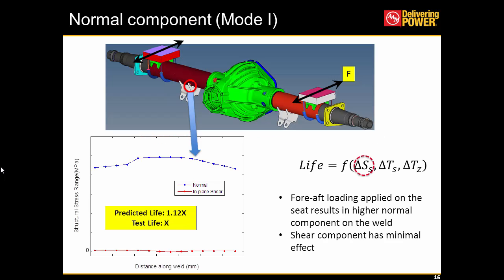So first, I have a situation with a mode 1 dominant scenario. In this case, we are able to predict the location of which weld is going to fail. In this particular case, a rear axle where the shock bracket weld is failing, it's dominated by normal structural stress. The shear effect is minimal, and we are able to predict it pretty well against the test.